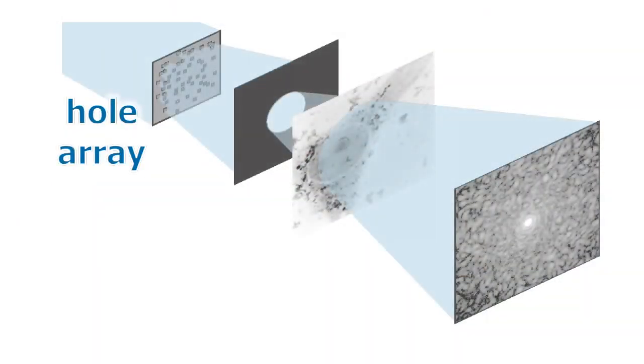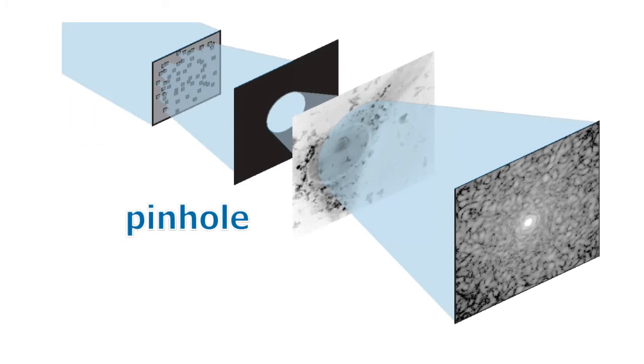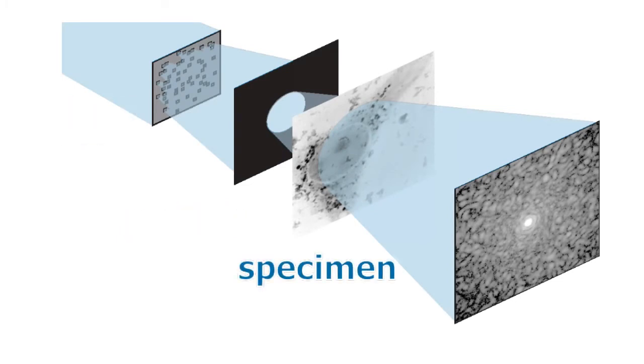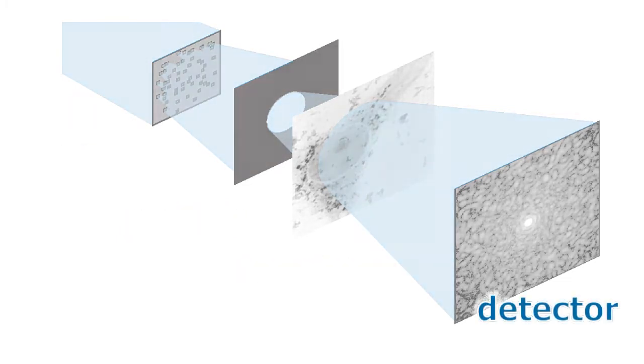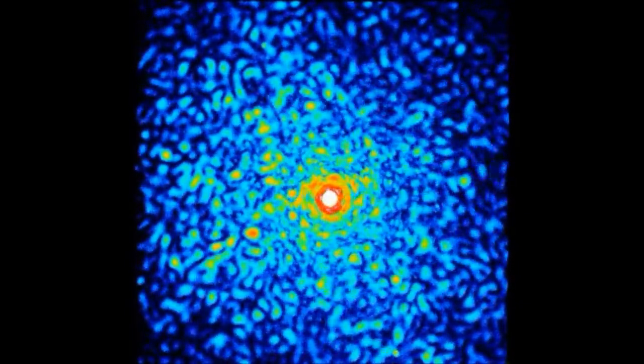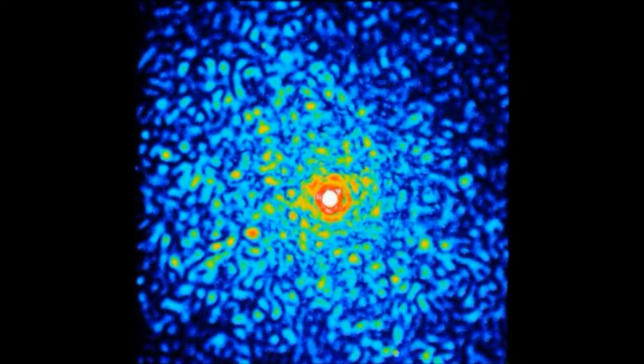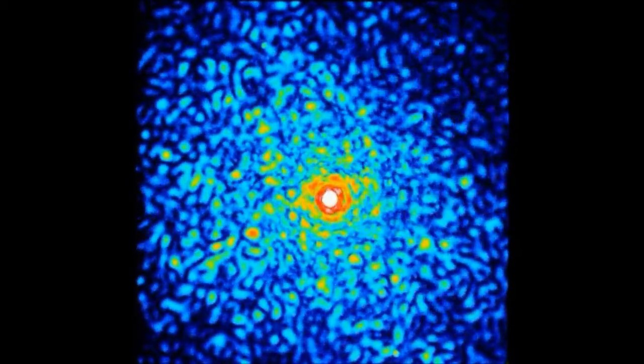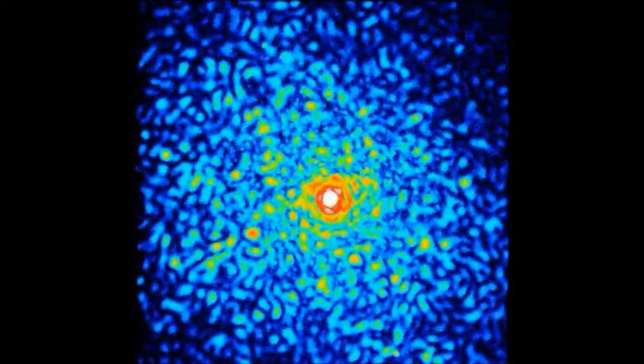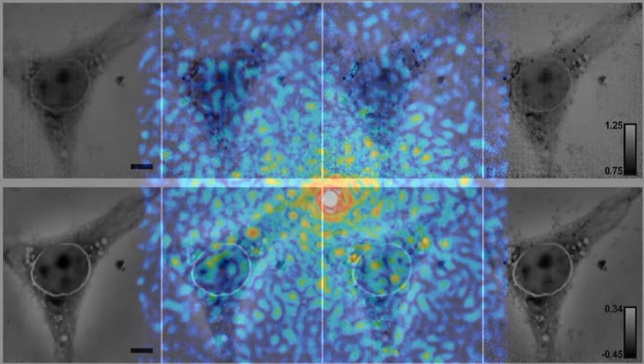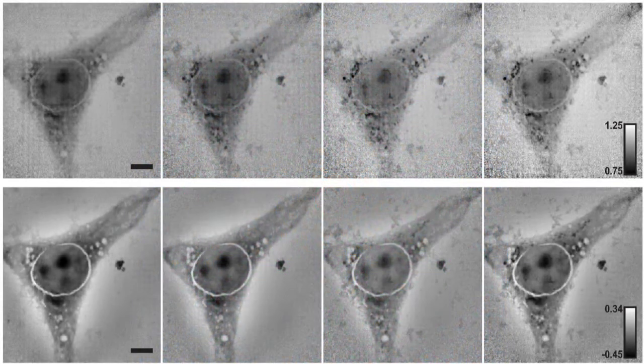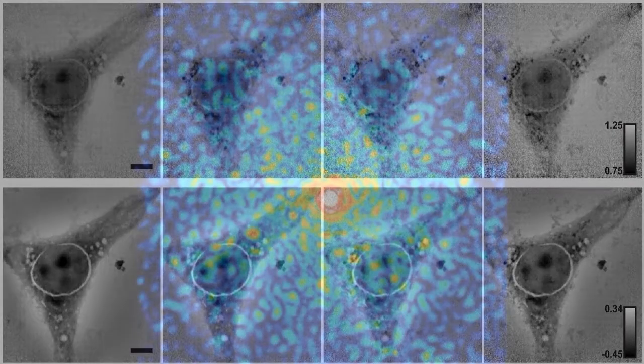The technique involves successively illuminating overlapping regions of a specimen with a coherent probe and recording the resulting diffraction patterns. It is important that the illuminated areas overlap significantly, since those common regions provide duplicate information that allows computer algorithms to reconstruct reliably both the sample transmission function and the illuminating probe.